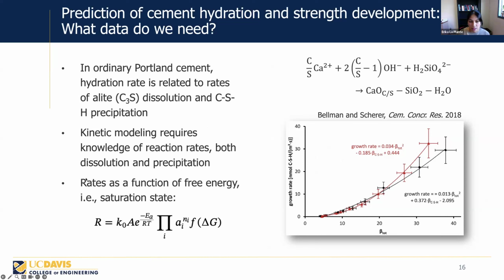So in this context, the rates would be expressed as a function of their free energy. This is a general rate equation that describes mineral dissolution and precipitation. And you can see this dependence on delta G, which in this case is the saturation state. This treatment has been applied for CSH, for example. This is the growth rate of CSH as a function of beta. Beta here is an expression of the saturation state. So you can see as we increase the supersaturation with respect to CSH, we get an increased growth rate as well.